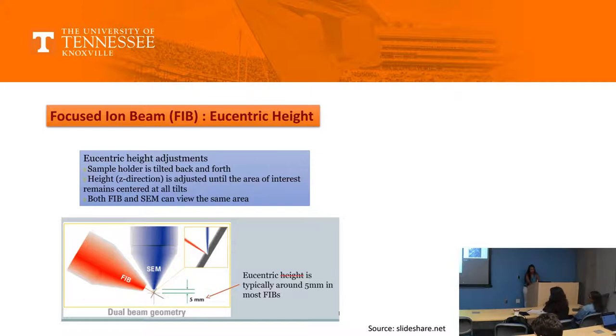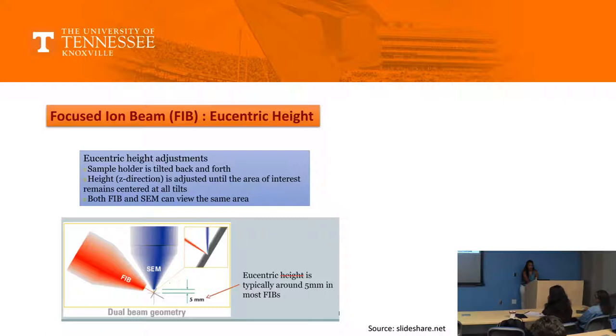Everything is extremely delicate inside the microscopes. That's why it keeps on breaking, because we have multiple users, the entire university uses it, people break it. So there's a reason why we approach this condition that the microscope is not working for another week. So we try to be very careful when we take out the FIB. We back the gun very, very carefully. And this is an important distance that you will keep in mind while operating it. This is important because both FIB and SEM are looking at the same zone. So you're using two guns to look at the same zone. The gun that is looking is also milling at the same time. That's why you're able to have the entire view.